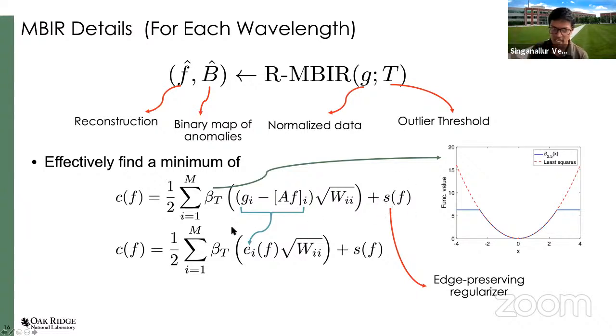So that is the key contribution. We said that when we have this type of data, it might be useful to put a different type of cost that effectively removes the influence of large measurements that don't fit the forward model very well. So we're doing a kind of band-aid solution where instead of adjusting the forward model, we're adjusting the penalty term so that we can reject measurements which are due to the crystalline nature of the sample. And once we have that, we have a cost function which we have to minimize. Now this is a non-convex problem.